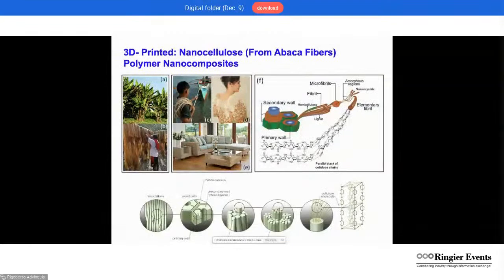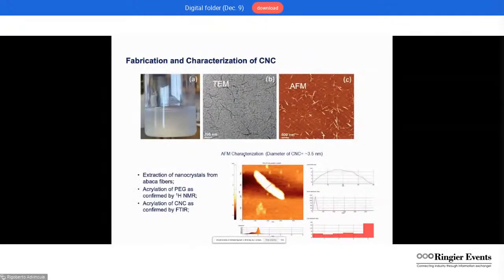So several stories here are based on research that I did with some visiting scholars from the Philippines. So for example, nanocellulose, which is derived from abaca or coconut, can be derived by breaking down the cell wall, lignocellulosic sources or fibers, which can in turn be broken down into elementary fibril and then eventually the nanocellulose material. So specific plant sources have a variety of nanocellulose structures. In the case of abaca and coconut coir, we can derive nanowhiskers, as shown here, with a high aspect ratio as observed by transmission electron microscopy or AFM. So this nanocellulose, we can mix it with the resin used for 3D printing in ratios from 0.1 to 5%.